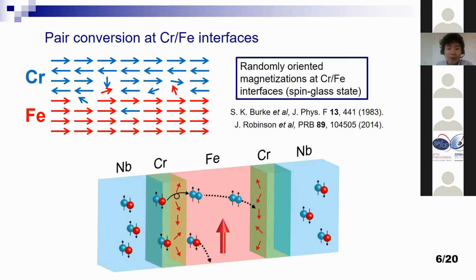And recently, we are using chromium iron interfaces because this is a convenient structure. As you know, iron is of course a ferromagnet and chromium is a weak antiferromagnet. At this interface, spins are randomly oriented and frozen. So we have a so-called spin glass state at this interface, and the magnetization here is intrinsically inhomogeneous. If we inject singlet pairs to this interface, we can convert spins from antiparallel to parallel. And if we prepare this kind of structure, we can observe long-range Josephson current flowing through thick iron layers.